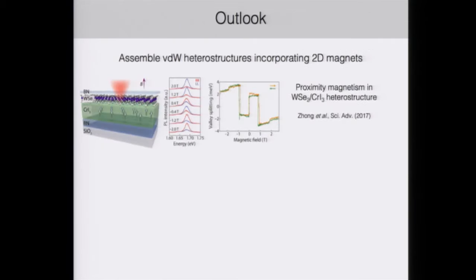Moving forward, now that we have 2D magnets at our disposal, we can begin to assemble van der Waals heterostructures that incorporate these magnets. So some earlier work by Xiaodong Xu's group shows proximity magnetism in a monolayer tungsten diselenide heterostructure placed on top of a thick slab of chromium iodide. They're able to observe valley splitting due to proximity magnetism from the underlying magnet.